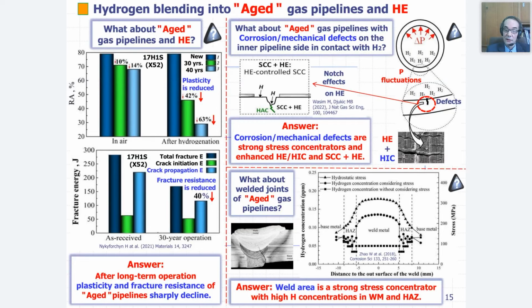So the answer is that pre-existing corrosion mechanical defects are a strong stress concentrator and strongly enhance hydrogen embrittlement, hydrogen-induced cracking, and also stress corrosion cracking plus hydrogen embrittlement, as you can see on the slide which explains the notch effect. So that kind of defects are notch and stress concentrator.